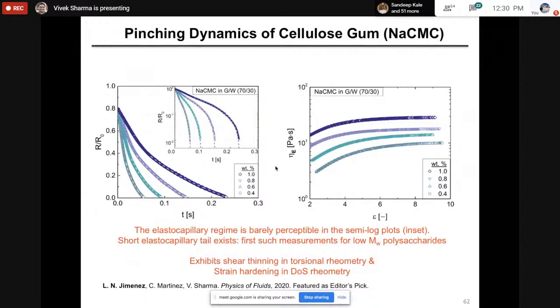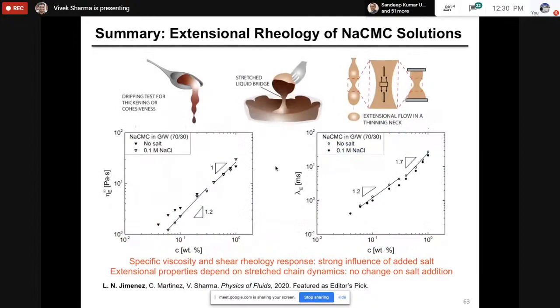So we carried out experiments to measure the actual neck thinning dynamics, and it involves a fair bit of detail, but the summary from the extensional rheology characterization was that because the extensional properties depend on stretched chains, and the stretched chain size does not change when you add salt, we got more or less the same response in extensional rheology with and without salt. And this is again something that's important if you're trying to think about designing things as dipping sauces or even dispensing fluids.